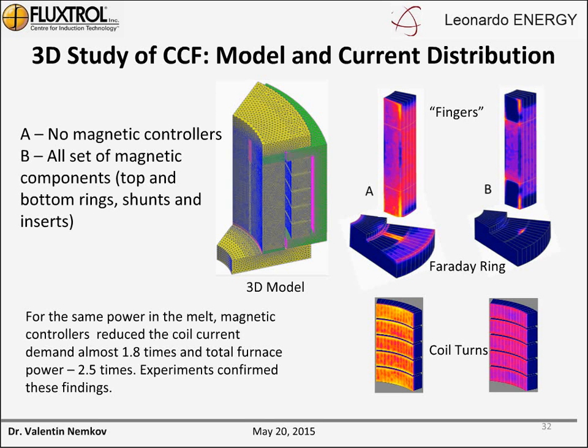The portion of the finger with current density color map, then the color map of currents in the Faraday ring. You can see a very bright strip with high current density, which is just under the slit in the cold crucible. And you can see on the bottom the current density in the coil.